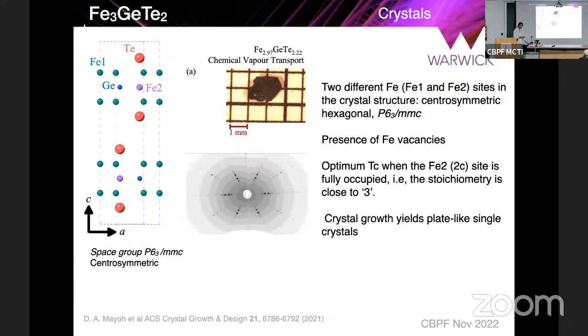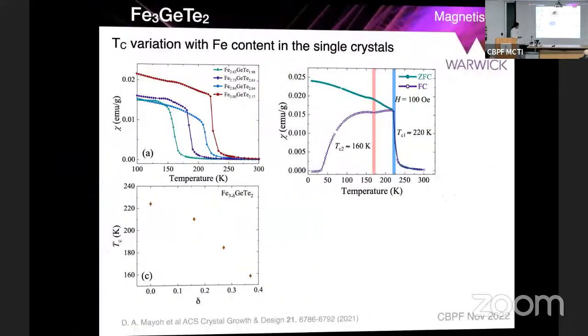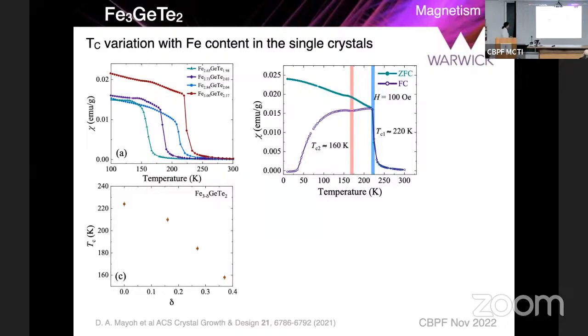So these are all plate-like crystals that form quite nicely, okay? What we have done is determine what composition of iron, germanium, and tellurium you need to start with for these crystal growths in order to get the optimum TC. And if you look at this, you'll see that we are even able to control the actual iron content in the materials and therefore obtain a range of crystals with varying iron content. So you have varying TCs, okay?